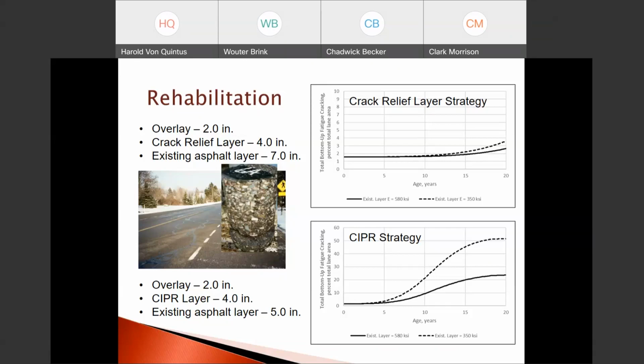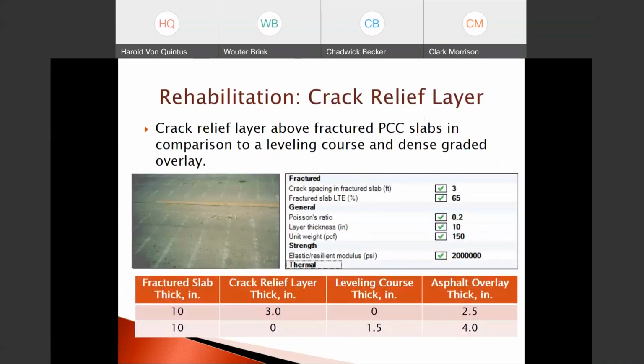graphs. For the rehabilitation design strategies, the upper one is using the crack relief layer of 4 inches and an overlay of 2. And then the lower is using a cold in place recycling of 4. And in this case, we only have 5 inches remaining of the existing pavement layer and a 2-inch overlay. So the condition of the existing pavement, as well as the reflection cracking mitigation strategy, can make a big difference in our rehabilitation design. They're both important.